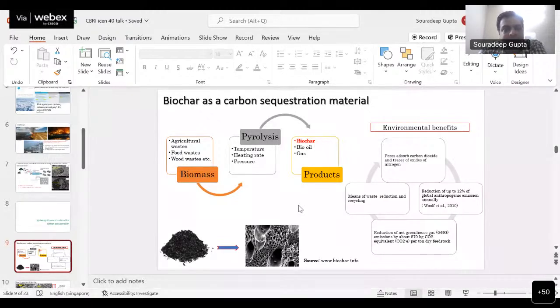There is a difference. The difference is that biochar has to be produced under a certain set of conditions. Why? Because the conditions, for example, temperature, heating rate, and pressure, will influence the development of the porous network in the biochar. And these pores play a very unique role in that they have very high affinity for carbon dioxide and other such gases, and they can be captured through adsorption in the micropores of biochar, right? And this whole process can give us three components: biochar, bio-oil, gas, and of course the residual heat. And if we take into account the utilization of all the three components, the whole process can be carbon negative.